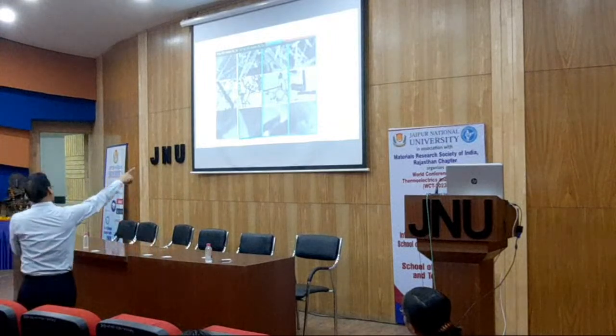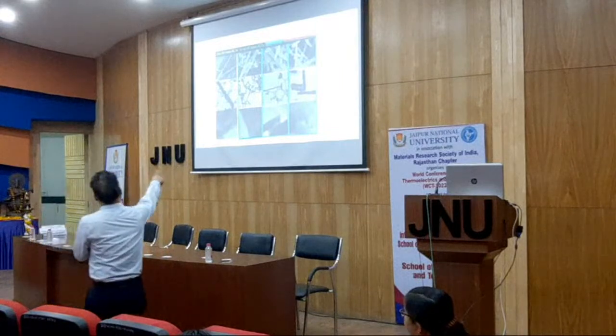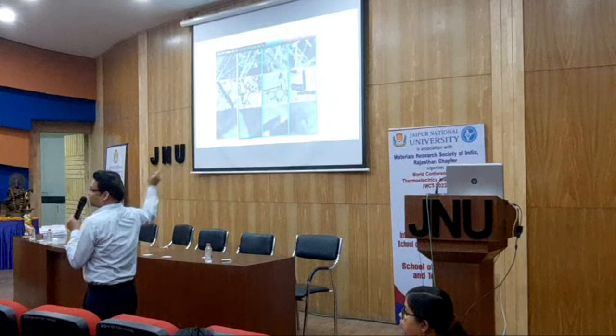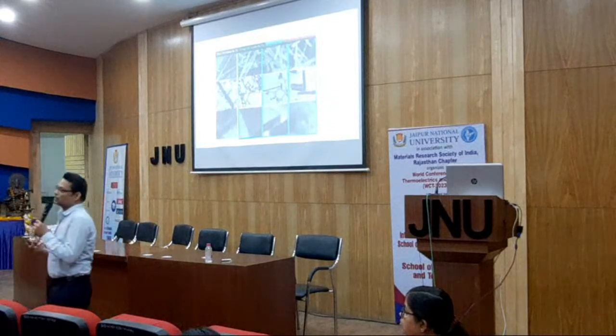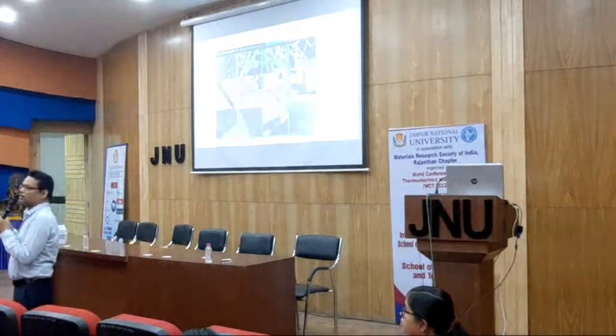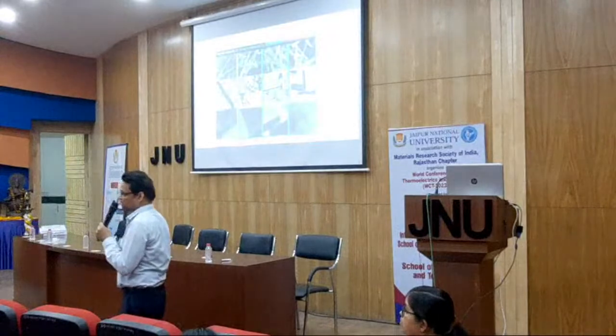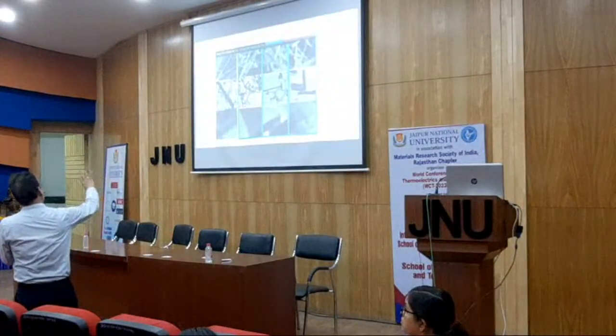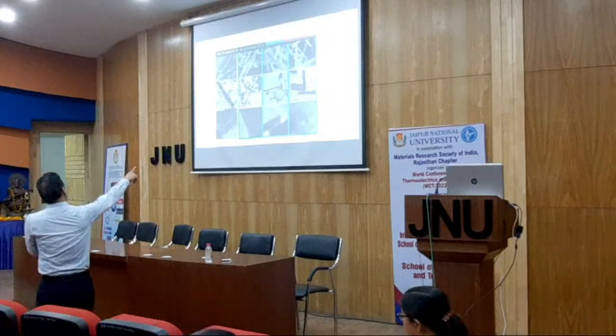Which is not in the 10 mg RGO, though some dislocation and defect is there, but in comparison to the first one and last one, it is a little bit better microstructure, less disorder as compared to that, because we want to retain the electrical conductivity of reduced graphene oxide, which should not be hampered by this doping process due to bismuth telluride, right? So in that case, we do the HRTEM, reduced graphene oxide 5 mg and 10 mg, the last two figures.